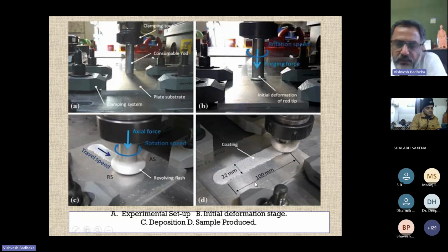But when you cut the cross section, what will happen? At the interface, the bonding will be less than even the rod diameter. Say, for example, your rod diameter is 18 millimeter, and what you are getting deposited here is close to 22 millimeter. But when you cut the cross section at the interface, the bonding will be less than the diameter of the consumable rod, 1 or 2 millimeter less.